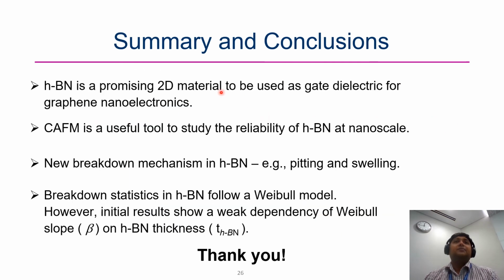So finally, this is the summary. What we have seen is that HBN is a promising 2D material which can be used as a gate dielectric for graphene nanoelectronics. We have also seen that conduction AFM has proved to be a very useful tool to study the reliability of HBN at the nanoscale, especially at this initial material growth stage. We have also been able to understand the breakdown mechanism using conduction AFM in HBN, and we see that both swelling and pitting are dominant mechanisms. Finally, we have seen that the breakdown statistics in HBN follow a Weibull model. However, our initial results do show that there is a weak dependency of the Weibull slope on the thickness, and it needs to be further investigated.